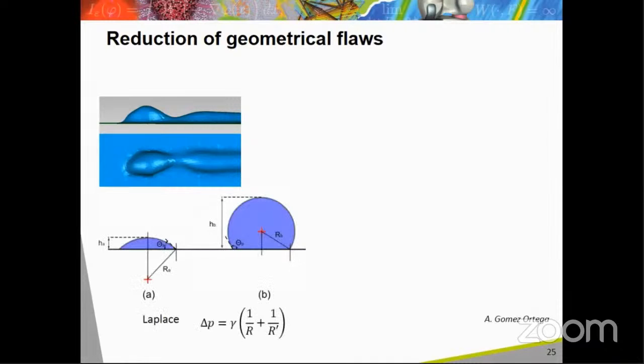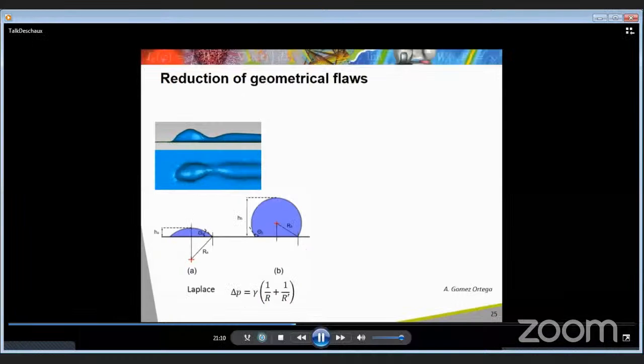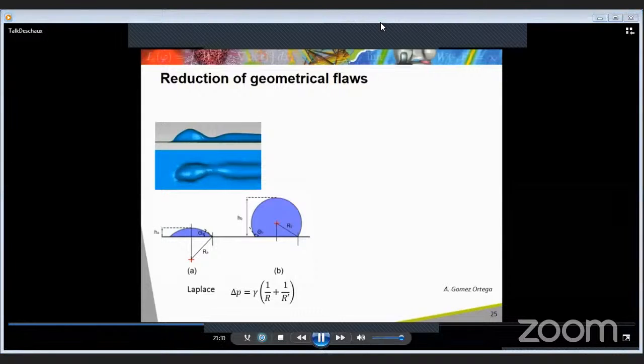Indeed, the pressure variation in the liquid deposit can be expressed with a Laplace equation that indicates the pressure in the liquid increases when the curvature radius of the liquid-gas interface decreases. In this figure, one can see that if the contact angle of the liquid deposit on a solid substrate is higher than 90 degrees, an increase of the bed height creates a decrease of the radius, and then a pressure increase. That promotes the formation of a constant height all along the bed, and so a regular deposit.